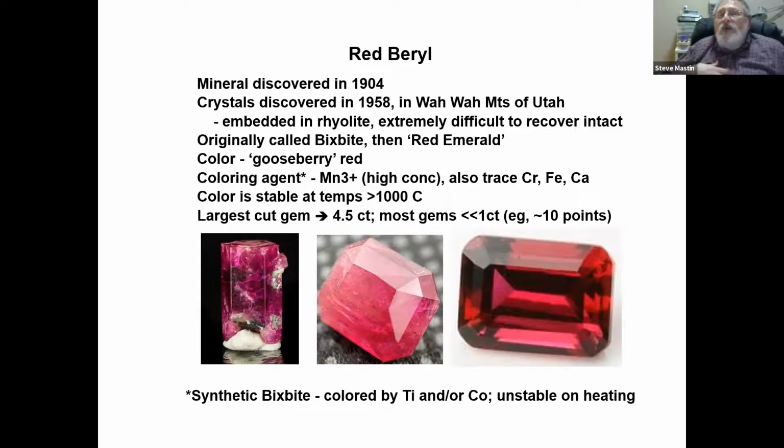And that's the biggest one in my collection, but they're real, they're not synthetic. That beautiful cut gem on the right is probably, at the very least, an enhanced red beryl, but more likely a synthetic one. And the difference is that the color in the natural ones is stable at very high temperatures, but the synthetic ones are almost never stable at high temperatures.